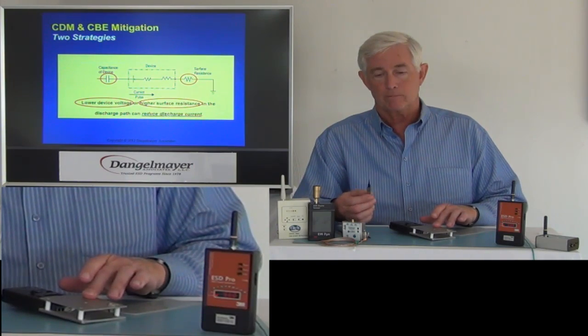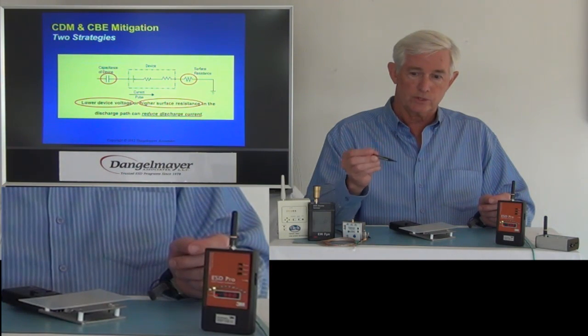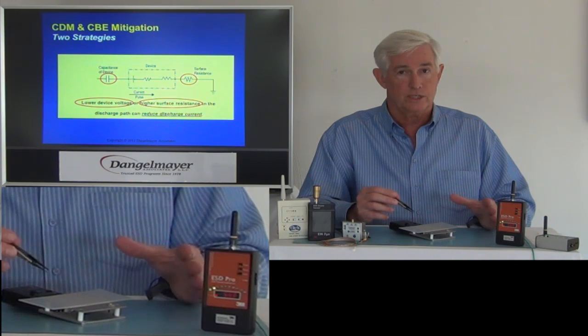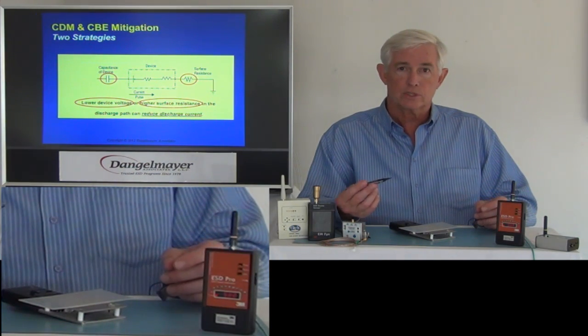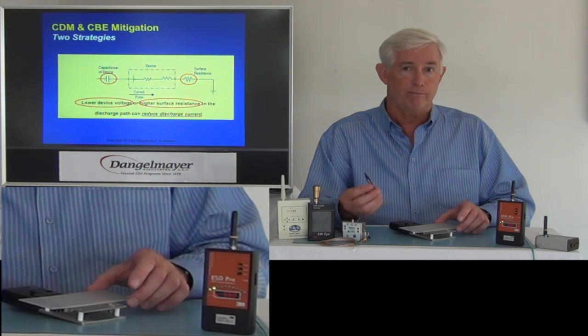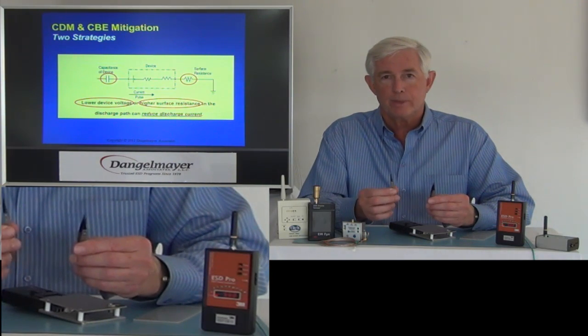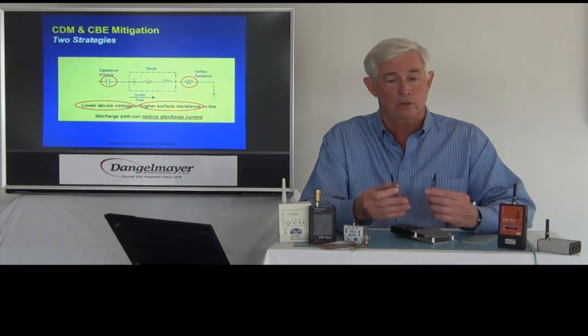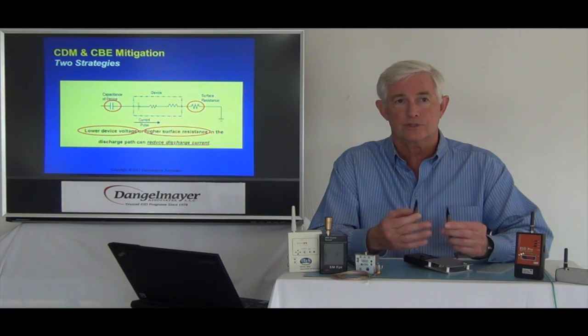Now let's repeat it a third time. I'm going to bring this plate to the same potential and take this third pair of tweezers — another black-tipped pair — and touch the same surface. There was a discharge, but it did not trigger an ESD event strong enough to be detected by this event detector just a few inches away. Therefore, this tip has reduced the discharge current to a safe level for virtually all operations and applications. Now, why do these two behave differently? This pair is carbon loaded, and there can be hot spots that trigger high discharge currents even though the resistance properties may be acceptable on average. This pair is a homogeneous material made out of ceramic that will give you consistently reliable protection of your devices and very, very low discharge transients.